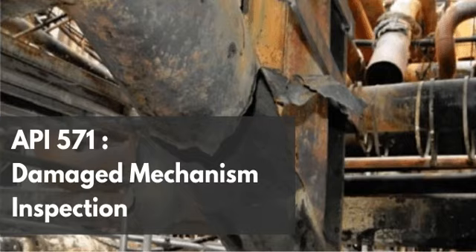It really is. Carbon steel with PWHT is vastly cheaper on initial capital expenditure. But if you have a highly restrained field tie-in on a critical FCC overhead system, where the historical operational data proves the sour water pH frequently touches 8.5, relying on field heat treatment is an enormous gamble. So upgrading to an alloy 400 or a clad 300 series stainless steel bypasses the mechanical restraint variable entirely. You change the rules of the game completely.